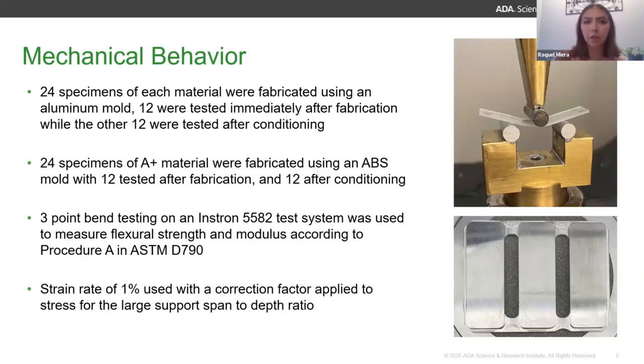So for mechanical behavior, 24 specimens of each material were fabricated using our aluminum mold, and 12 were tested immediately after fabrication, while the other 12 were tested after conditioning. Then we fabricated an additional 24 specimens of our A+ material using our ABS mold, with the same 12 tested after fabrication and 12 after conditioning. We used 3-point bend testing on an Instron test system to measure the flexural strength and modulus according to procedure A in ASTM D790. We used a strain rate of 1% and then applied a correction factor on stress for the large support span to depth ratio.